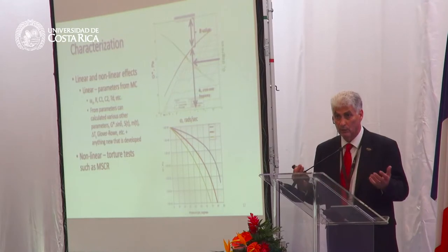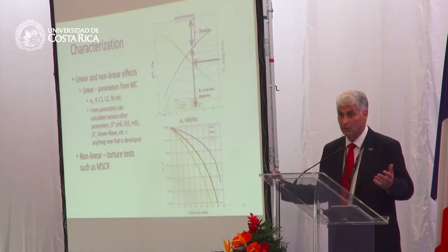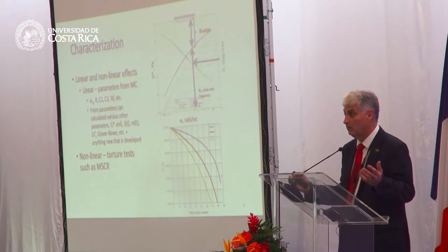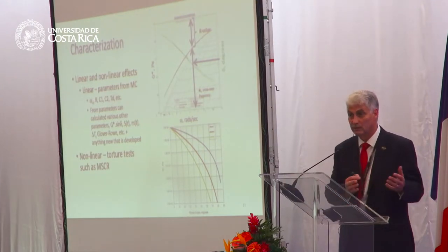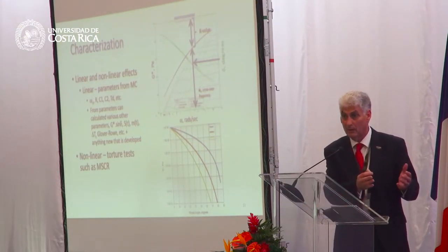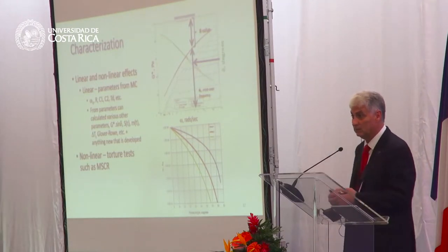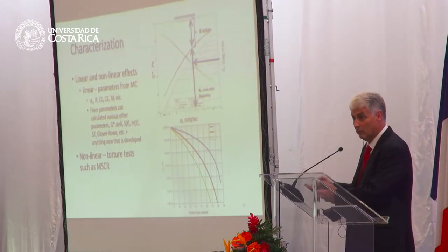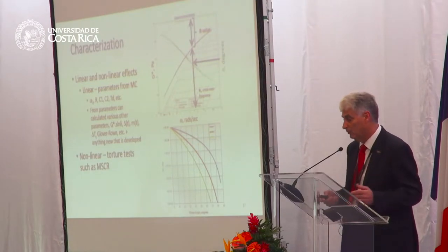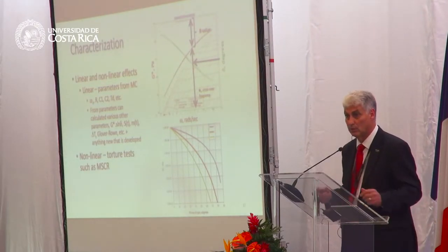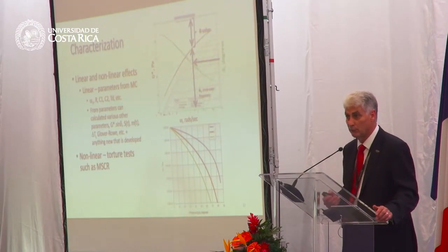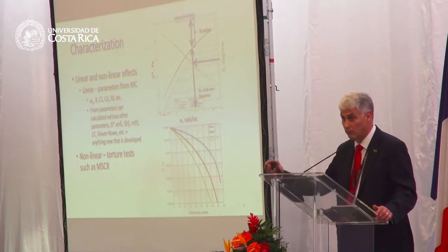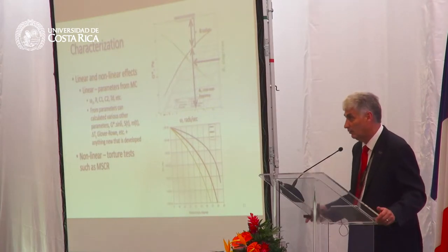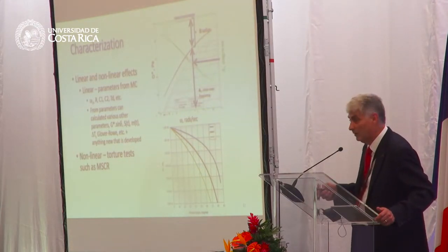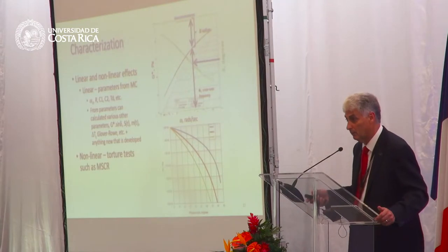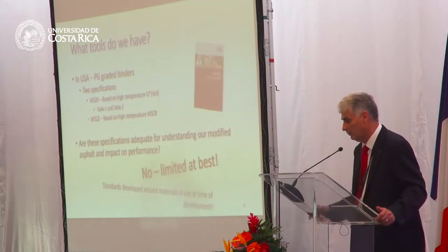So when you look at the rheological information, you can start to tell almost immediately things about the production process of a binder. And likewise, if you have information about the chemistry, you can start to guess some of the information about how the binder is physically going to perform. Some folks have developed very good procedures for doing this. The work at WRI can nearly predict your G star and your phase angle. If you put in some chemistry information, they can calculate all of this. So this is the way the industry is going. We're going to be developing this information, and we're going to have very good information about doing it.